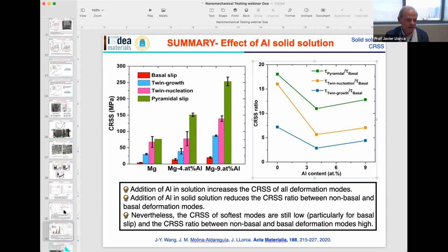We see that. So basically, we were able to measure the critical resolved shear stress for basal slip, twin nucleation, twin growth, and pyramidal slip in magnesium 4 atomic percent aluminum and magnesium 9 atomic percent aluminum, with just a very, very small effort as compared to all the effort you would need if you had to cast the different aluminum magnesium alloys and cast crystals with different orientations.